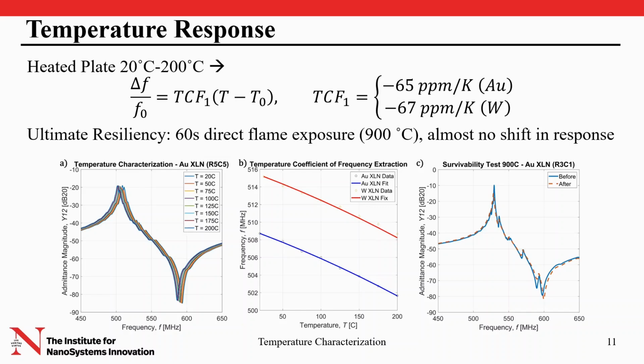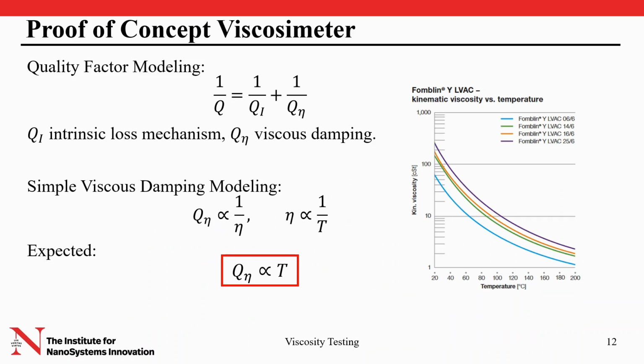Lithium niobate is indeed pyroelectric. However, in this case, we're using very small chips, and besides this ultimate resiliency test, in our application we do not expect any abrupt change in temperature. Therefore, the pyroelectricity effects should be minimal. As a matter of fact, even though we shifted the temperature from 20 to 900 degrees, the chip survived, both the resonator and the chip itself. These preliminary results are very, very encouraging, and they led us to develop a proof of concept viscometer.